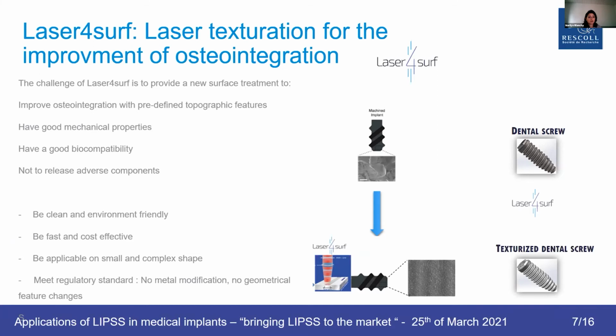So the challenges we thought were very important for Laser4Surf, as a new surface treatment that could be used for medical implants, are, of course, first of all, to improve the osteointegration with predefined topographic features. We should show that they have good mechanical properties, especially after a few months of implantation, bringing on the bone to implant contact. We should show very good biocompatibility, and finally, it should not release any adverse components.